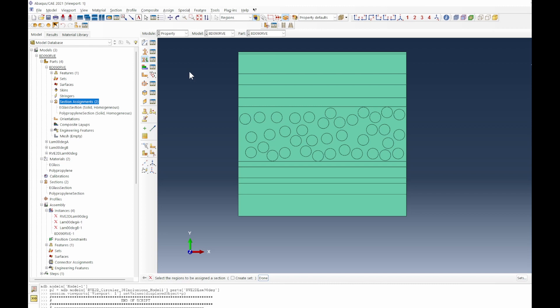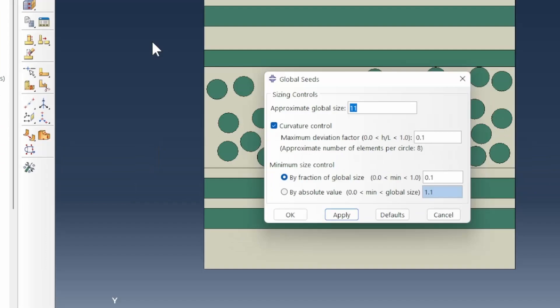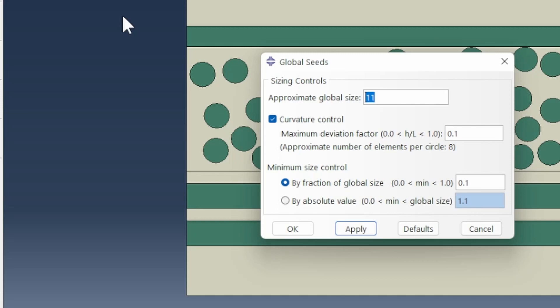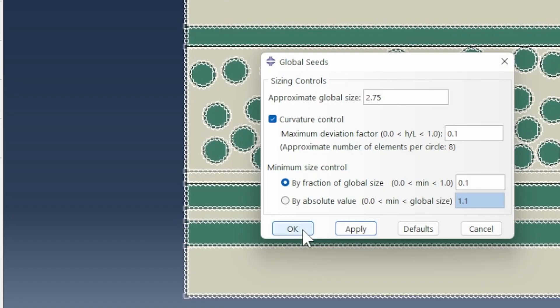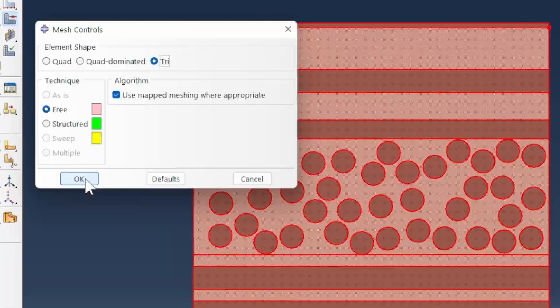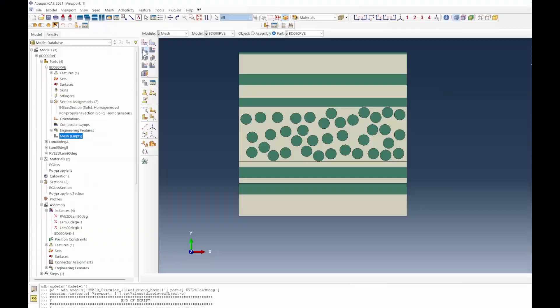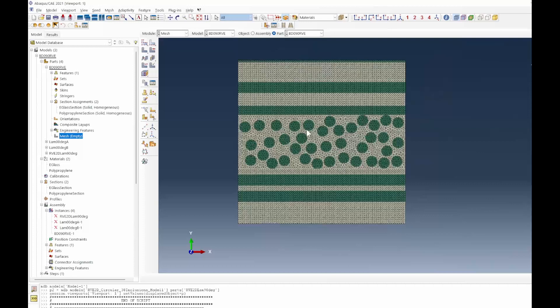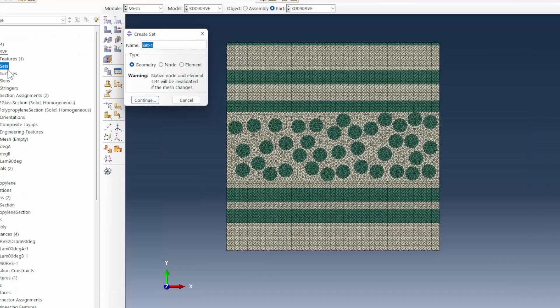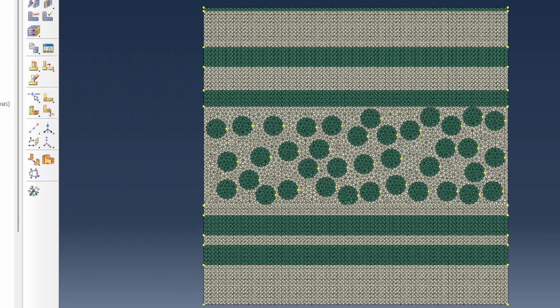The next step is to mesh the domain. We select the part and specify a mesh size of 2.75 microns for a fine mesh of this structure. We mesh using triangular elements and proceed to mesh the domain. We get a good result showing all the fibers in the RVE. Then we select all four corner nodes — pressing Shift to select them — as we need them for applying boundary conditions.